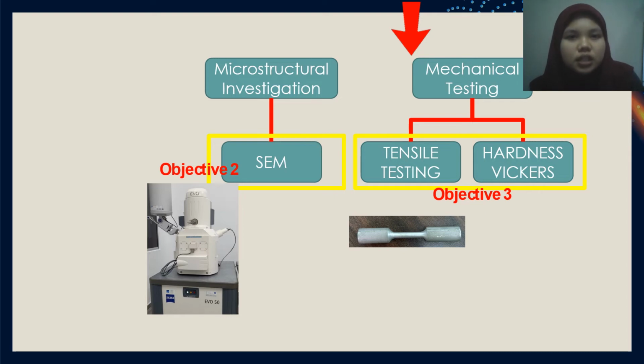And next, for the mechanical testing, I used the tensile testing, which is the UTM, Universal Tensile Machine, and the samples were prepared firstly by using the CNC turning machine with ASTM E8M standards, and also hardness Vickers by using ASTM E384 standard, which were my third objective.